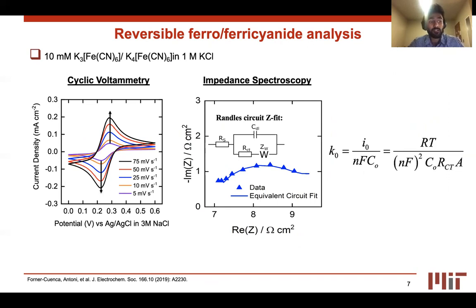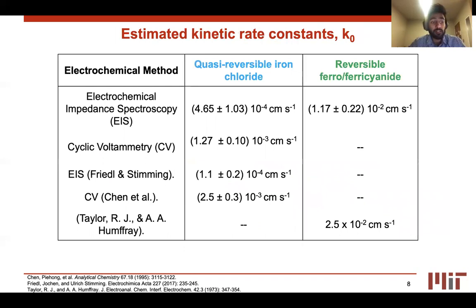Finally, the kinetic rate constant for the reversible regime was calculated using the equation as shown. Using the traditional methods of cyclic voltammetry and electrochemical impedance spectroscopy, the estimated kinetic rate constants obtained for the iron-based electrolytes are shown in the first two rows. As referenced in the table, these values are in agreement with previous work reported in literature, which validates the kinetic model developed to estimate the electron transfer kinetics for flow battery electrodes using dense carbon films.